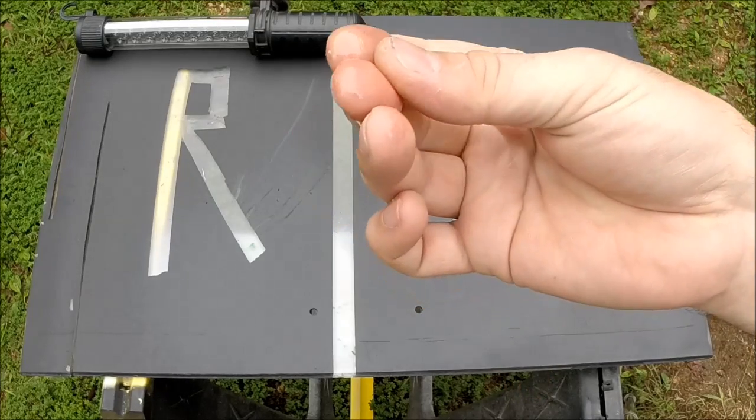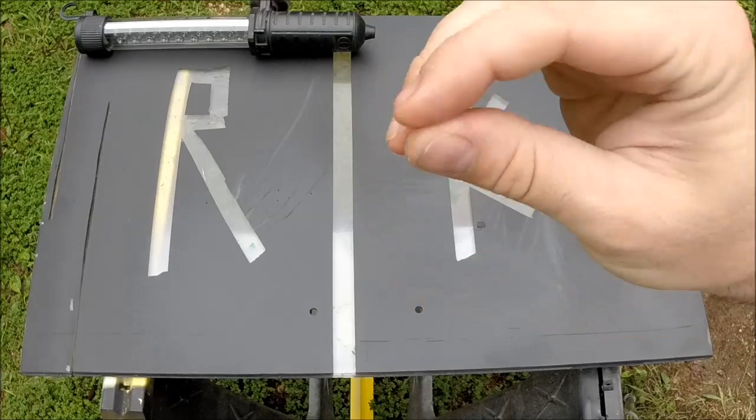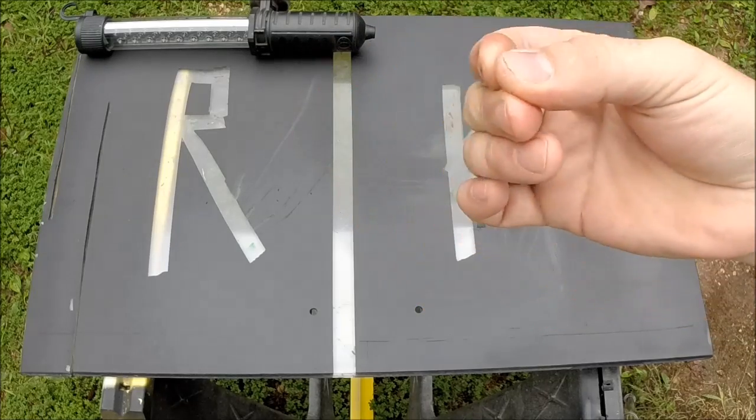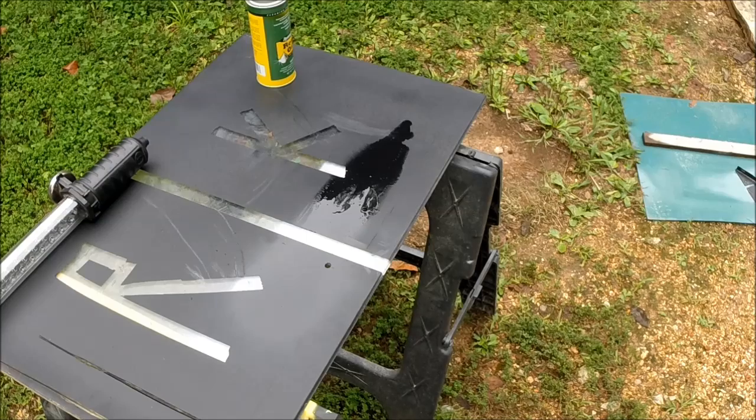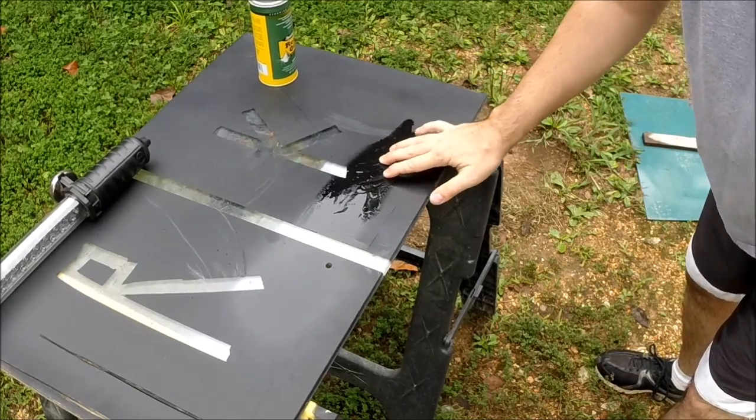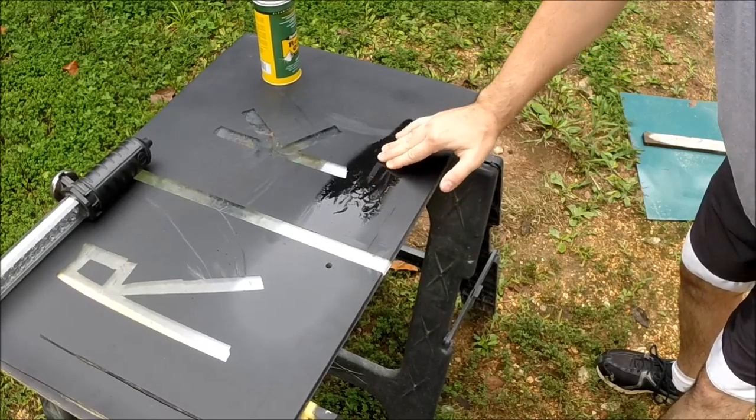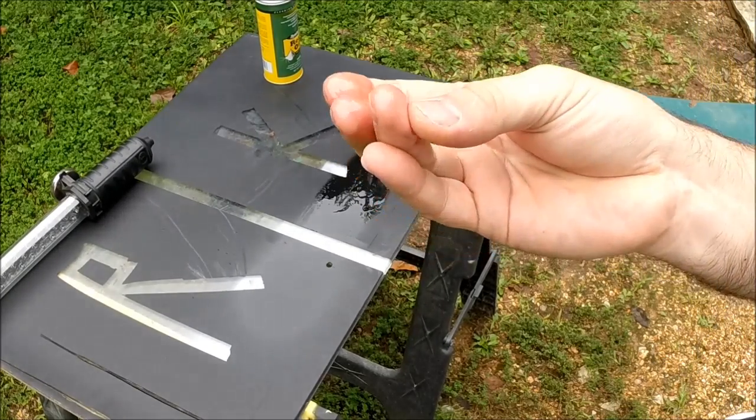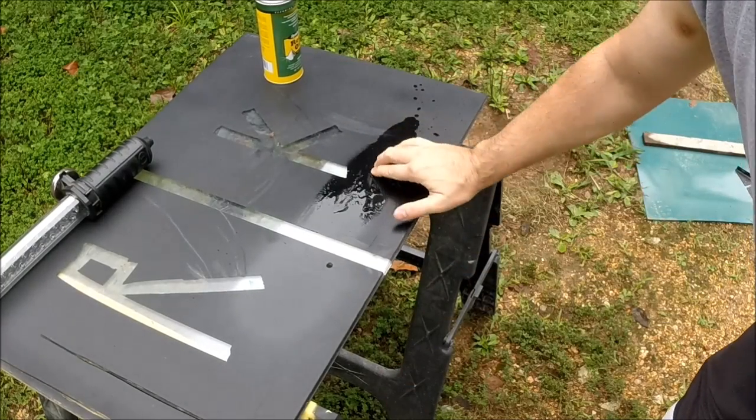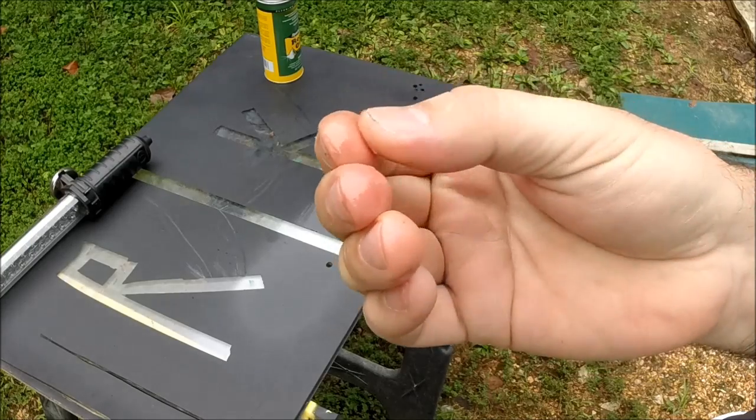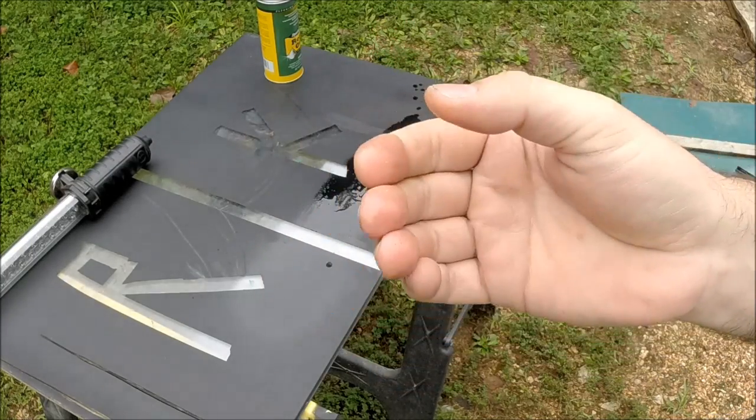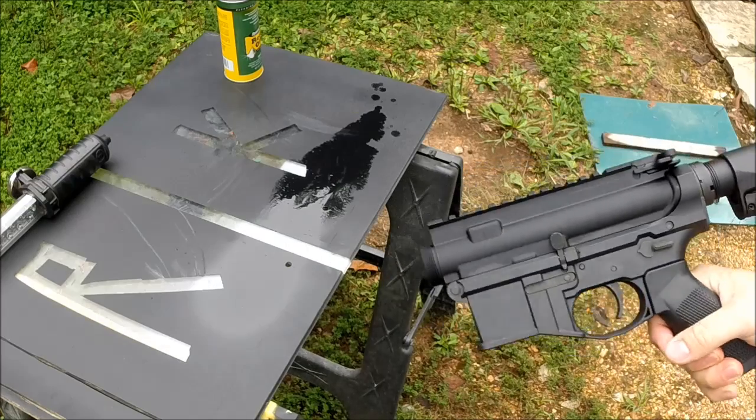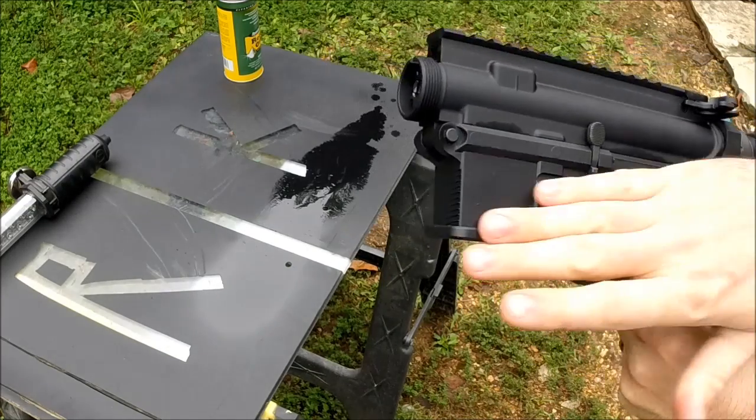As you can see, Krylon is impervious to the Rem oil. It's been on here for about 30 minutes now. Nothing. I think I had a flake on my finger of the old stuff I scratched off, but it would be turning my fingers black if it was actually dissolving, but it's not.